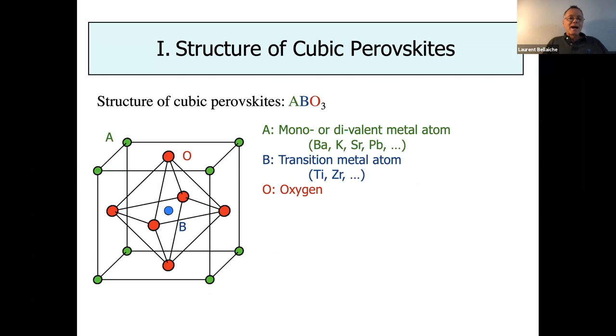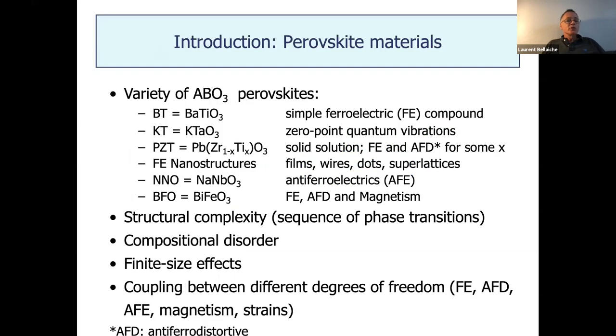About the perovskite, I think a lot of you know it has a simple chemical formula, ABO3, with A and B cations and O the oxygen anions, in a high symmetry cubic structure, with A at the corner of the cube, B at the center, and the oxygen ions at the middle of the faces. Very simple structure, but quite a lot of diversity among ABO3 perovskites. For example, barium titanate is a prototypical ferroelectric. Potassium tantalate, also a perovskite, is a very interesting system known as an incipient ferroelectric or quantum paraelectric. It means that quantum effects, namely zero-point phonon vibration, kill ferroelectricity.